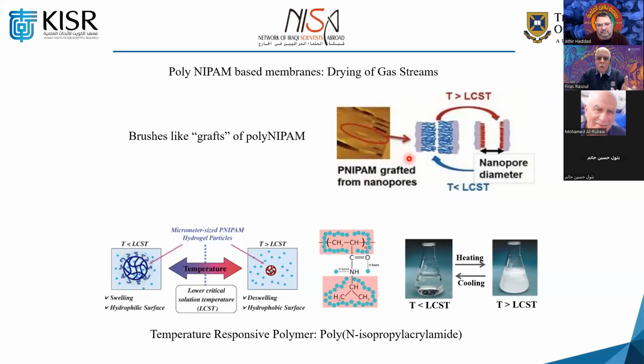And of course, when the temperature is low, this is very solubilizing, and the polymer chains are floating. Then when you pass any liquid, for example water or moisture, it will capture it and swell. Then, of course, when you finish drying, you take that membrane and heat it up, not to a very high temperature, about 37 to 38 degrees centigrade. You find it will shrink and get rid of all the water which has been absorbed by the membrane. So this is one of the applications which is very, very interesting, I believe.